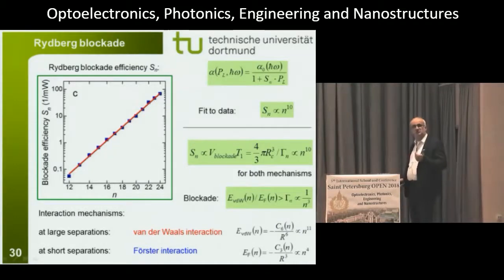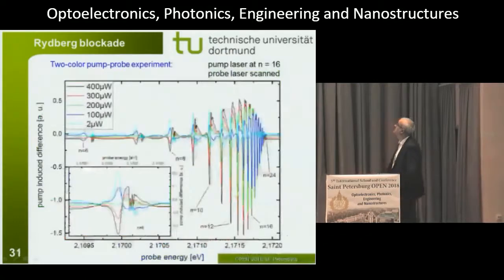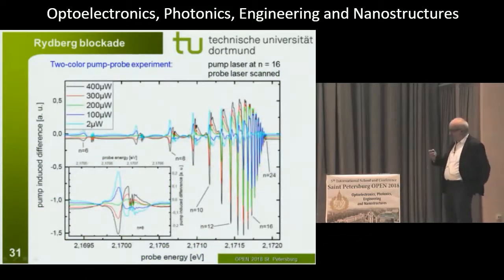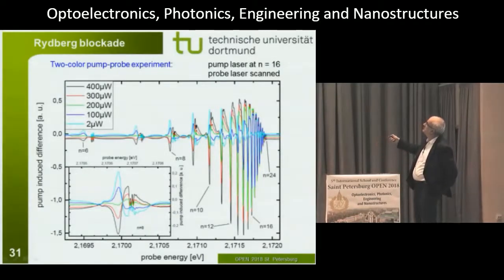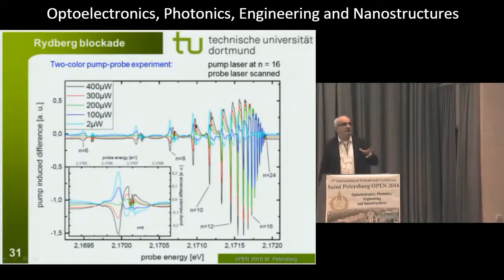And until recently, it was not clear to us how to describe exciton-exciton interactions. But this is clarified now. These are very recent results where we extended the experiment such that we use 2 color pump probe experiments. So we have 2 of these frequency stabilized lasers, and we fix the photon energy of one of these lasers to the n equals 16 exciton, to this state. And with the other laser, we scan across the absorption spectrum. This is basically a differential absorption. You see that when you pump here at the n equals 16 state with very low power, the absorption is slightly increased. But once you increase the power slightly, you see that all the peaks go into the negative range, which means all of them are bleached, and we get the Rydberg blockade for all these states.